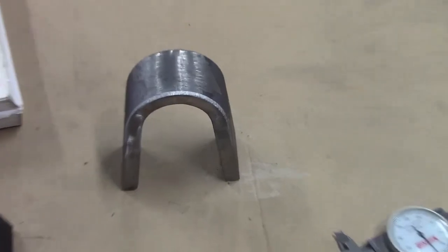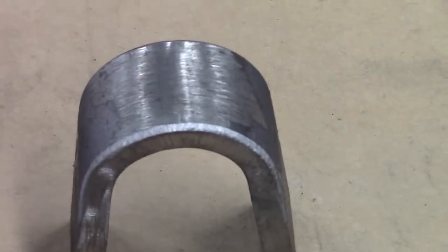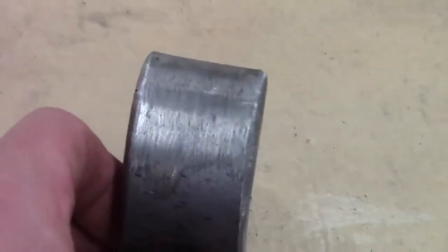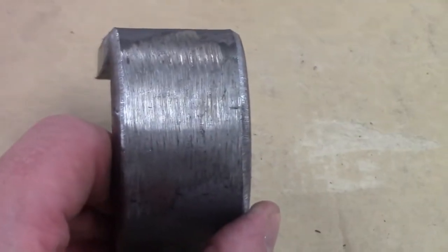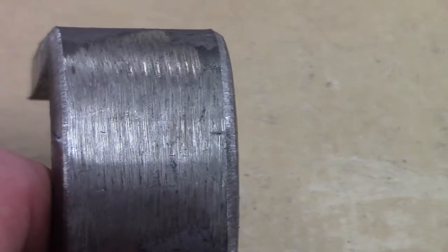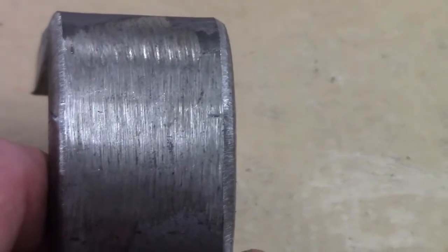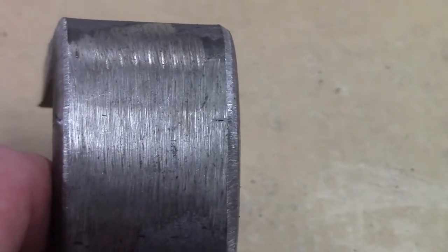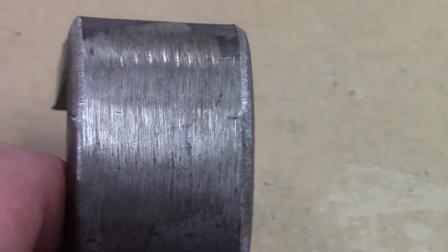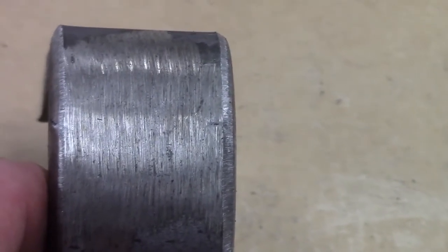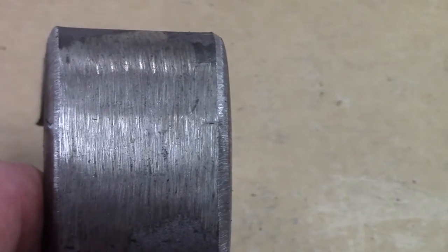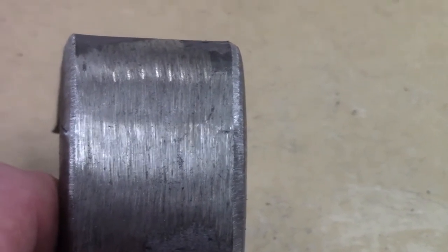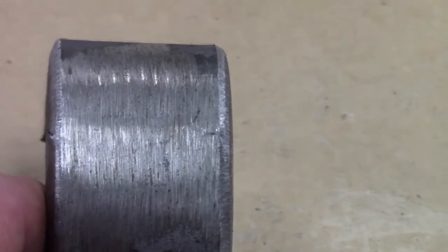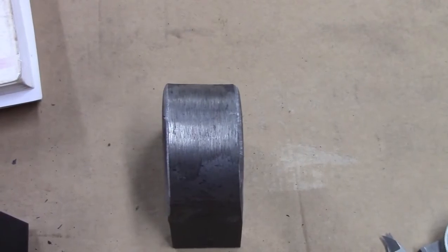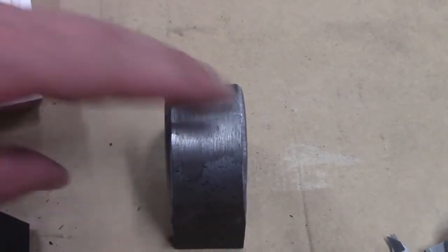Okay, this is the one bend that would pass. We're going to take it and turn it here. And you can see there's a crack right there on the end. We measured that out to be 0.105 inches, which is not greater than 1/8 of an inch. And by our code, it has to be less than 1/8 of an inch, or the sum has to add up to less than 3/8 of an inch. Okay, so the one on the side there is acceptable.